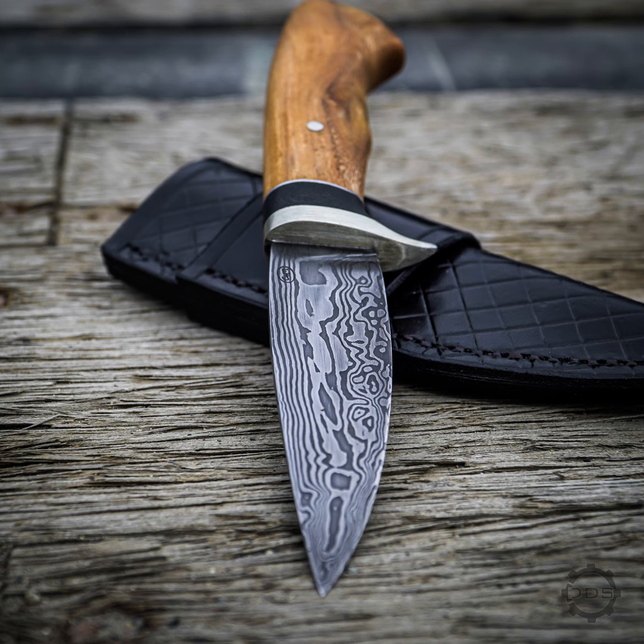I've done a little bit of testing with D2, which is almost stainless, and only hardened part of the blade. I don't know why people don't do more of that, but it's a general understanding that you do an oven heat treat, and it's very, very specific in an oven when you're working with really high alloy stainless steels and really high alloy tool steels as well. So you can more easily manipulate your basic high carbon steels.